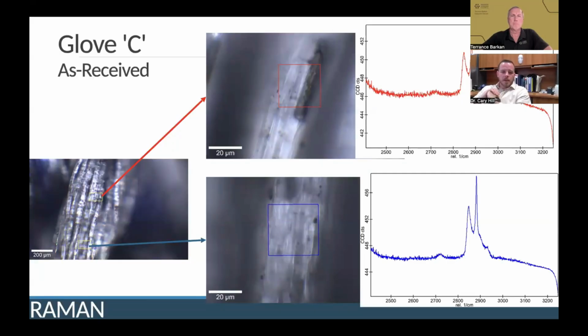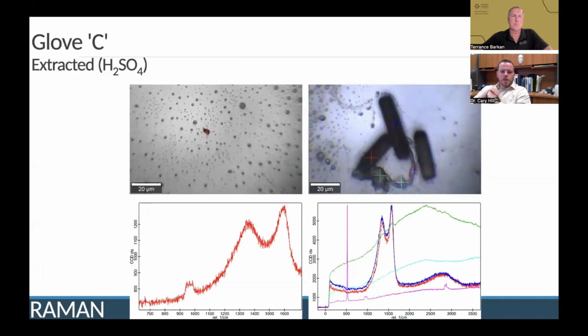Glove C, again, we see these kind of spots within. Raman doesn't reveal a whole lot. In the next slide, what we did find was evidence of carbon fiber. So this is one of the things that we found to be common. There are a lot of gloves that claim to contain graphene. They actually contain a different allotrope of carbon.